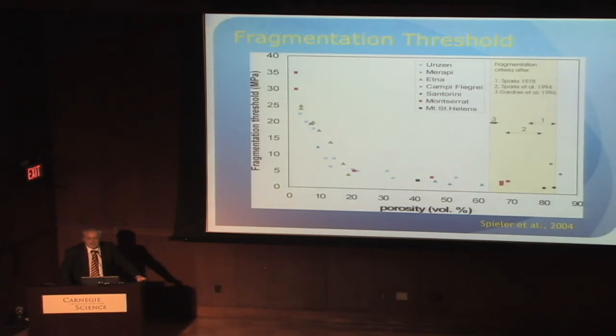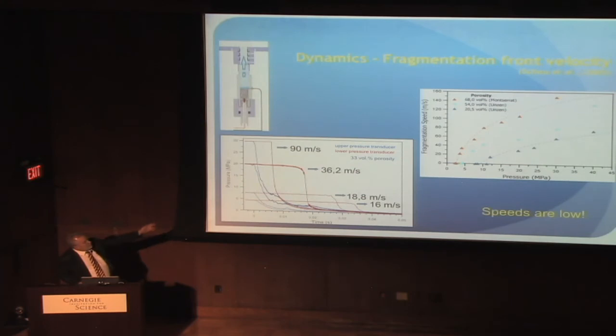At the point of the eruption and the explosive behavior of these systems, it happens so quickly, you've switched off all chemical reactions. No doubt chemical reactions have brought the system to the point where this is about to happen, most importantly, degassing and bubble growth. But that's now behind this system. Now it has to face the rapid decompression event, sometimes caused by itself, sometimes caused externally by a landslide, and when it hits that event, it happens so quickly that it's basically physics left over. Therefore, chemistry doesn't count, but physical properties, such as the number of bubbles in the material, do count, because that's where the overpressure lies. Fragmentation threshold, we called this. We had to come up with a name, and it sounded like a good name. You always know you're getting somewhere in science when you have to invent words, right?